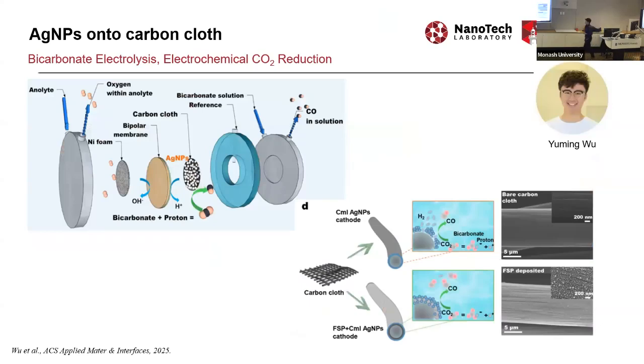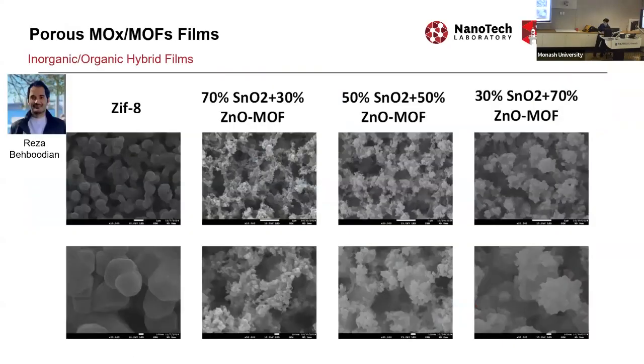We also use them for energy, and also for catalysis and electrolysis. This is one of the recently published works where you can even use a carbon cloth. That was a little bit tricky because it is quite sensitive to temperature, but we managed to deposit silver nanoparticles by flame on the carbon cloth and then use them for an electrolysis project.